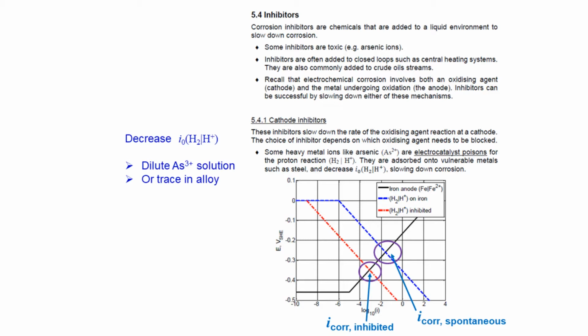A classic way of doing this is that I can do something really nasty: I can add dissolved arsenic 3+ ions into the water. This is something I can only do sometimes. Inhibitors like arsenic are suitable for recirculated water systems like central heating systems or cooling loops in a plant. It's not suitable for adding to an open water system because many corrosion inhibitors like arsenic - and I've deliberately chosen to show arsenic here to labour the point - quite a few corrosion inhibitors are toxic or bad for the environment. Nonetheless, they are often very suitable for adding to recirculated water systems that are sealed.